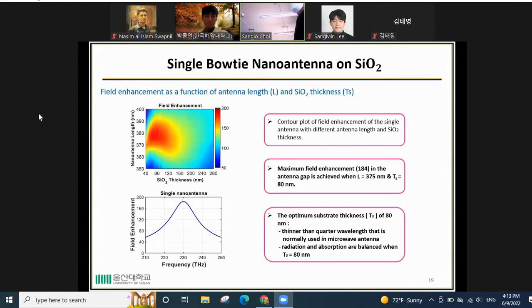This is the field enhancement as a function of the antenna length and silicon dioxide thickness. From this plot, we can see that the maximum field enhancement in the antenna gap is achieved when the antenna length is 375 nanometer with an 80 nanometer substrate thickness. You can see the field enhancement with this antenna length and substrate thickness is around 184. We need to note that the 80 nanometer substrate thickness is thinner than the quarter wavelength that we normally use in microwave antennas, because at this 80 nanometer thickness, radiation and absorption are balanced.